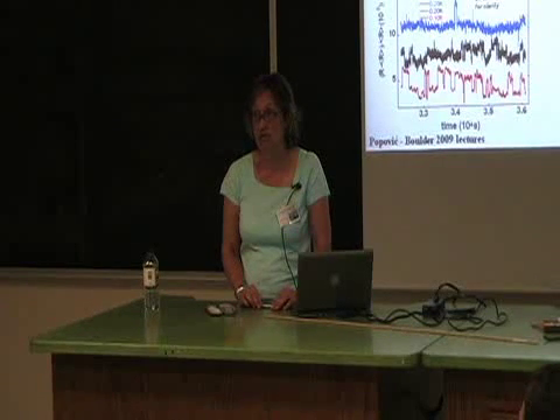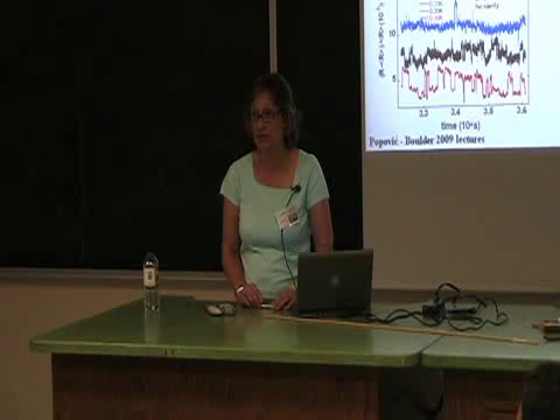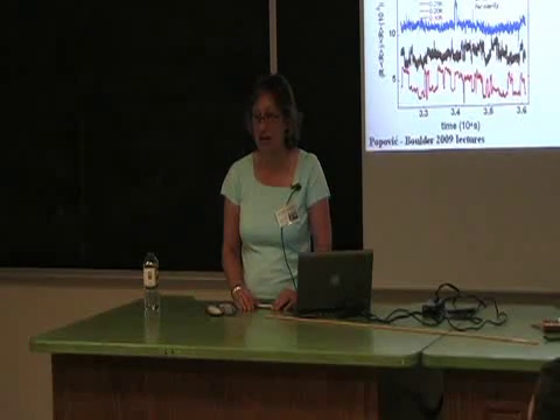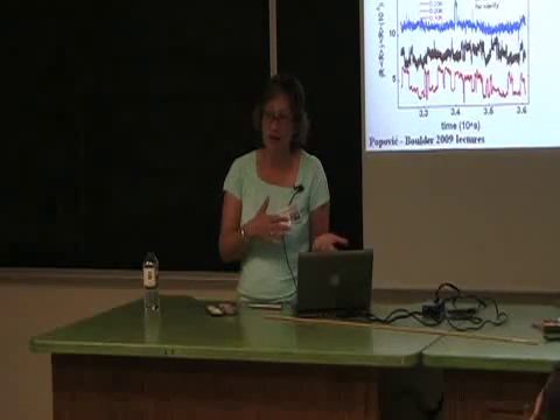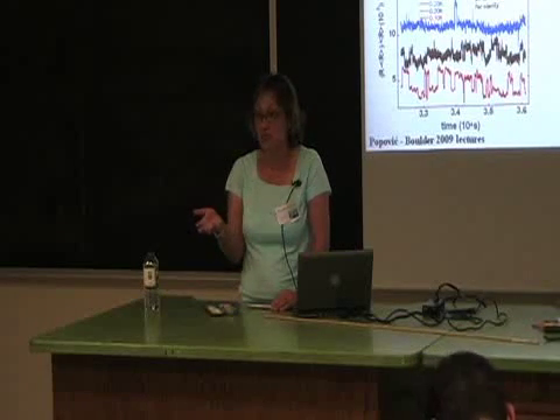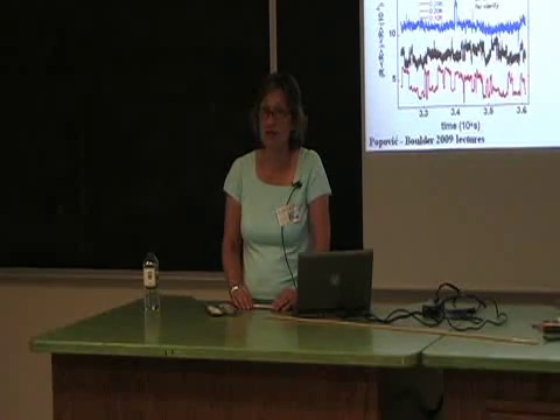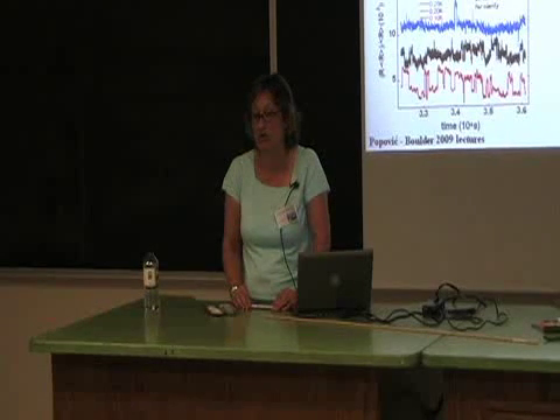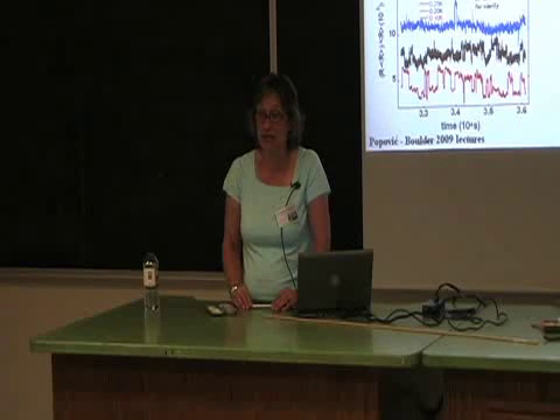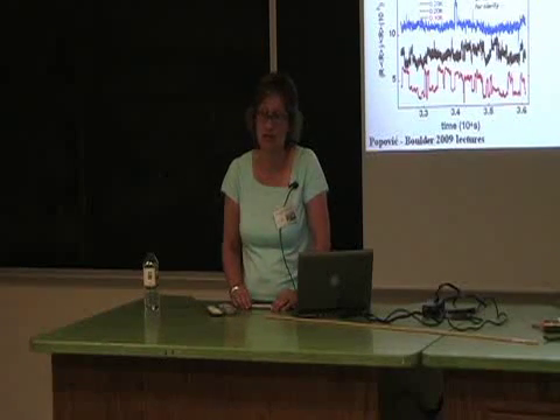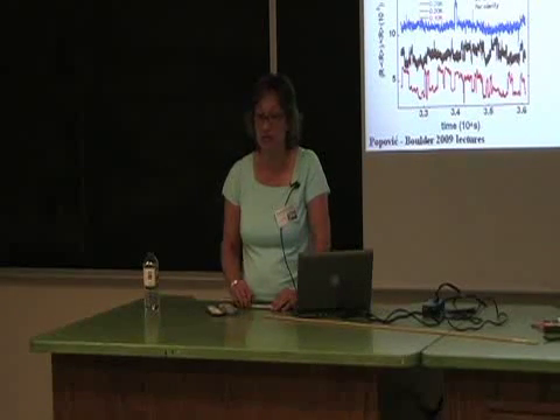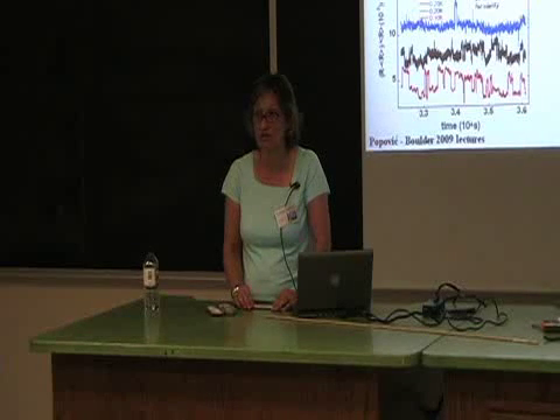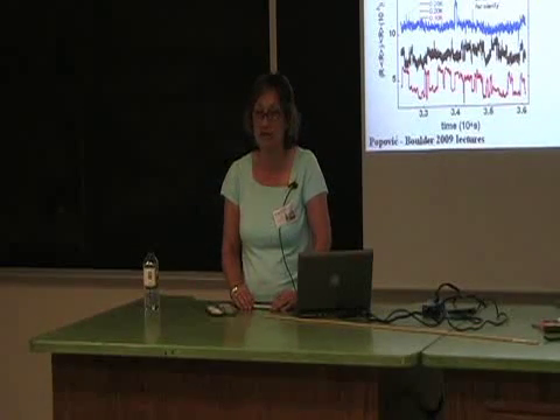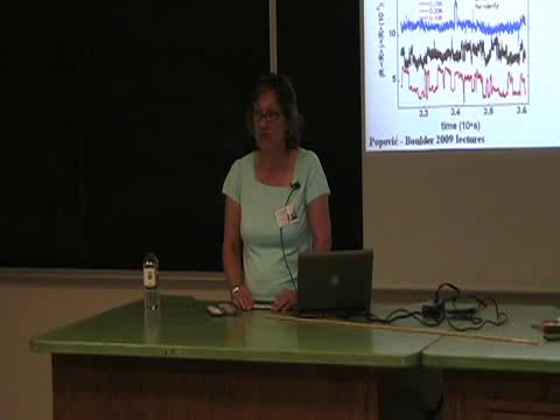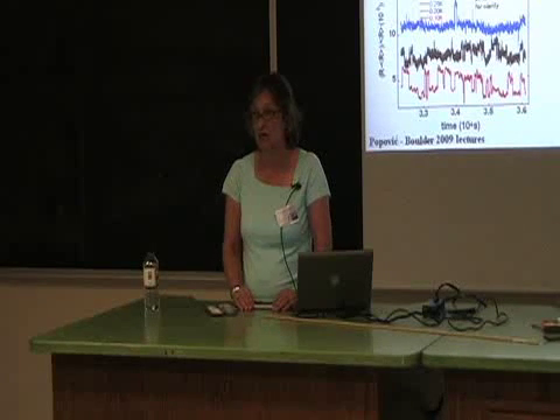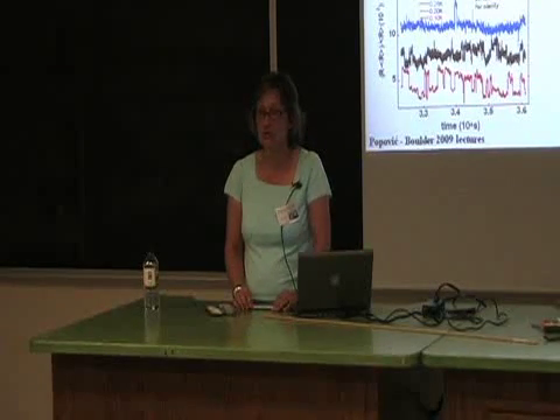It also affects the metal-insulator transition, and I know this also happens in doped silicon, that the system becomes more localized, the critical density goes up. But here it's the parallel field, so maybe it would not localize it. So maybe spin plays some kind of a role in that case. It has been shown that it reduces the screening. So you can say the effective disorder is bigger, so this is why the critical density is going up, and this is why this intermediate phase grows. This is a plausible explanation, and there is even one theoretical paper published on that. I think that's the most plausible explanation, that it affects the screening because it polarizes the electrons. But after you polarize them, nothing changes anymore.